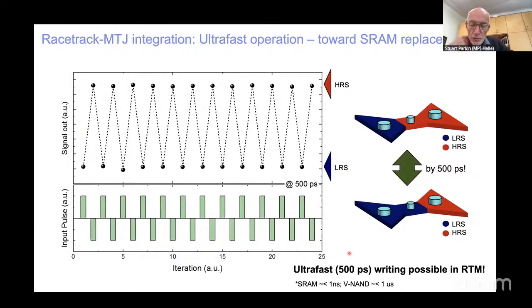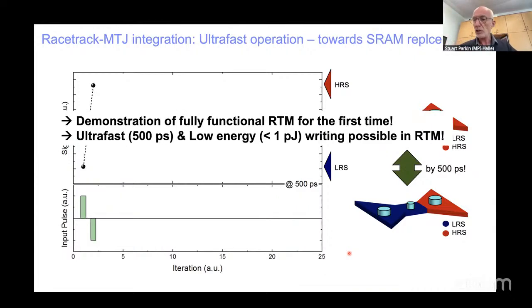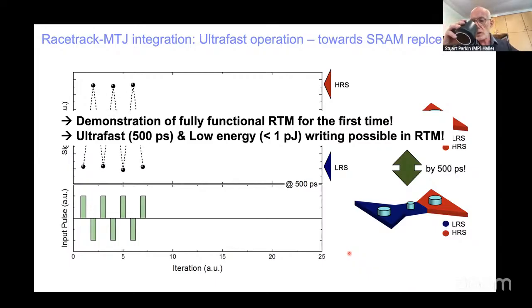And in this way, we've demonstrated we could build a racetrack with a single domain wall, moving it in a few hundred picoseconds from one end to the other, demonstrating a very dense and very, very fast non-volatile memory that could, in principle, compete with the fastest memory today, which is static random access memory, in a smaller form factor and with non-volatility. So we think this is also a very exciting development. So, demonstration of a fully functional racetrack for the first time; ultra fast and low energy writing is possible.